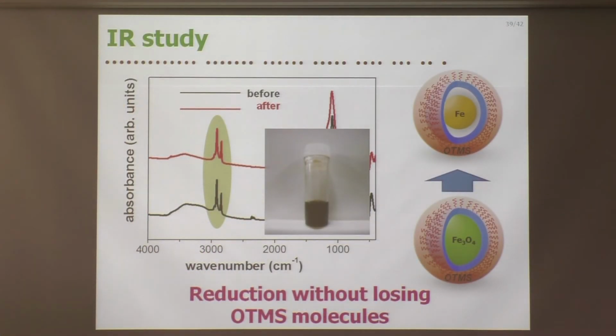Because the samples after reduction are modified with alkyl chains, they can form a stable dispersion in non-polar organic solvent. This is the image of a bottle in chloroform.